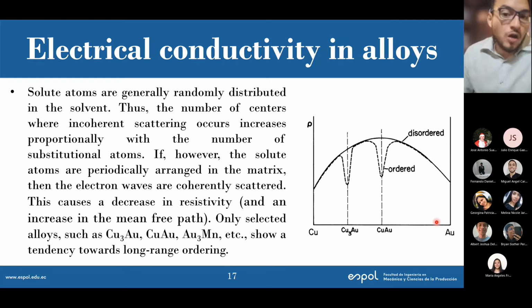The problem is that not all alloys show this tendency for long range ordering. You can say it's ordered, but maybe just in one part of the crystal, and then everything else is disordered. So that's not useful. It actually has to be a long range order. This arrangement has to be periodic. And if I have that, then yes, I will have this effect.